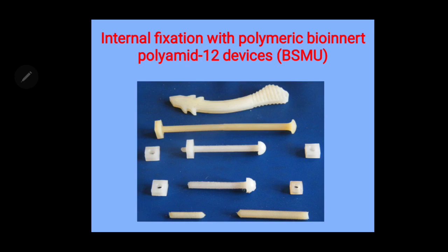made of this material. It is highly bio-inert and it can be present in the human body for many years without any problems. Actually, we did research on this, and up to 20, 30, even 40 years, these screws are safely present in the bone tissue after fracture healing, and there are no complications or adverse reactions.